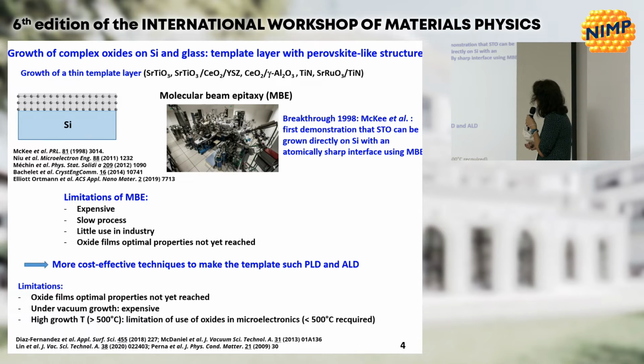Some other groups have worked with other techniques, like for instance, pulsed laser deposition and atomic layer deposition, with more or less the same limitations. The optimal properties are not yet reached. This is still under-vacuum growth, so this is still expensive. And also, it requires high temperature of growth, which is a limitation for the use of oxide in microelectronics.